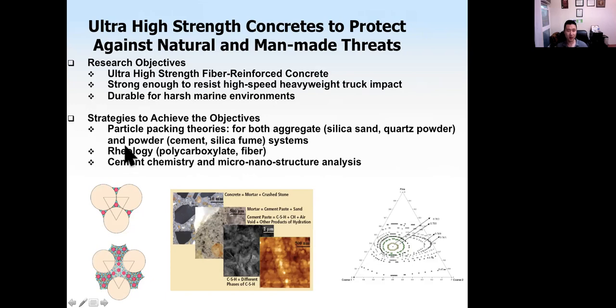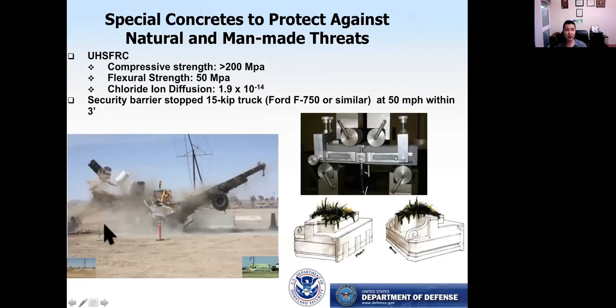We used particle packing theory, trying to achieve a very dense matrix, not only for the aggregate but also for the powder system, which means cement and silica fume. We focused on rheology behavior using admixtures and fibers, and also studied the cement chemistry to ensure the hydration product is strong enough. The end result is ultra high strength fiber reinforced concrete with compressive strength of more than 200 megapascal, very high flexural strength, and very, very low chloride diffusion rate, which means the concrete will be very durable also.